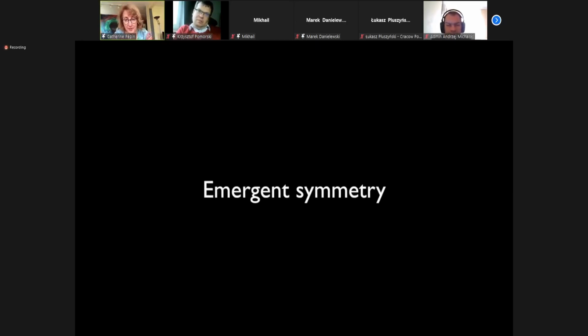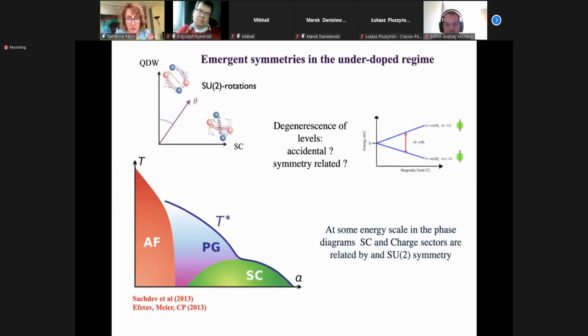In order to account for this, in the work we did with Constantine, we get an idea of an emergent symmetry. Say you have two orders that are degenerate, like in chemistry, where you have that a lot: a state which is degenerate and can get split, for example, with magnetic field. You sometimes have an emergent symmetry which enables you to rotate between one order and the other. Here, we take these two orders, bond density wave, which we call quadrupole density wave here, and superconductivity. The rotation between the two will be a typical SU2 group. This allows for a constraint, and this constraint will be responsible for the opening of a pseudogap at T star.